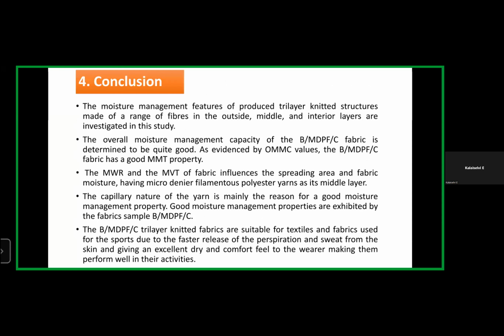Conclusion. The moisture management features of produced trilayer knitted fabrics made up of a range of fibers in the inside, middle and outside layers are investigated in the study. The overall moisture management capacity of the bamboo microdenier polyester filament and cotton fabric is determined to be quite good, as evidenced by OMMC values. The bamboo microdenier polyester filament cotton fabric has a good moisture management transmission property.